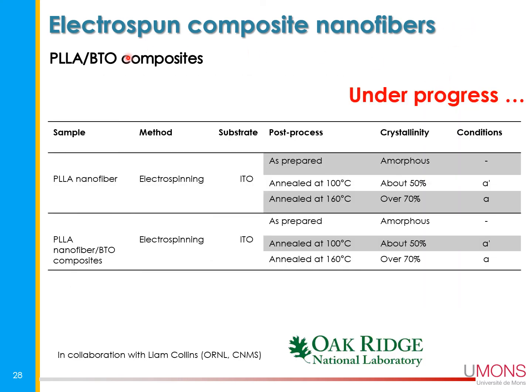But what Kyung did is to use PLLA. These are a set of samples, and for the moment those samples are moving to Oak Ridge, and thanks to the work of Liam Collins, the idea is to use up-to-date PFM technique to be sure that we are measuring correctly the PFM signal, as we saw before, and also during the other talks. The as-spun or as-prepared samples are most of the time amorphous, and to increase the crystallinity, which is the key parameter, as we saw before, we have to anneal the sample, and these are the sets of samples that are now being measured at Oak Ridge.